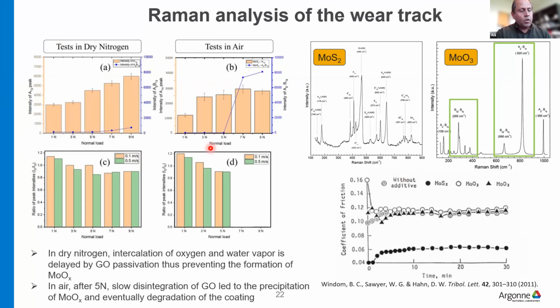Now, we did the characterization of the wear track in the dry nitrogen and in the ambient air. If you look carefully, you will see that these are the peaks corresponding to the MoS2, and the blue line plotted here is for the peaks of the MoO3, molybdenum trioxide. In dry nitrogen, we see an increase in the MoS2 peak, indicating that there is structural reorientation of the MoS2 going on, and very small degradation with the formation of MoO3, whereas in ambient air, we see that at 5 Newton, there is a sudden increase in the moly trioxide peak.